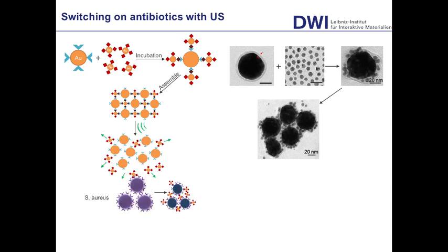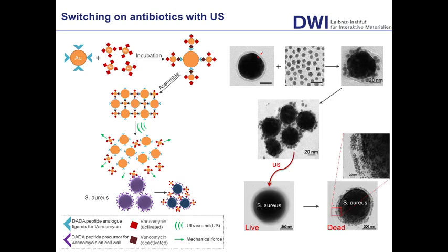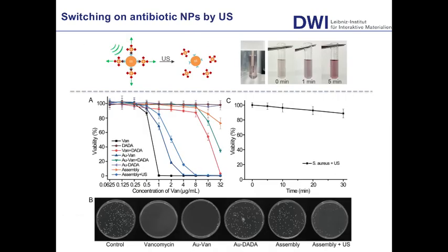And once you apply ultrasound, the aggregates get disaggregated, and then the small gold nanoparticles with vancomycin on the surface bind, for example, to Staphylococcus aureus, and by this, as you can see on the right-hand side, kill the bacteria. On this slide, you again see some technical details.